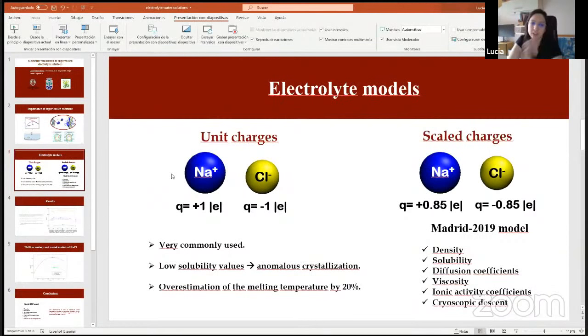Okay, so regarding the electrolyte models, we have unit charge models and scale charge models, and the first ones have been very commonly used, but they provide low solubility values, yielding anomalous crystallization. And one would expect that they at least would provide a good description of the solid state, but they overestimate the melting temperature by 20%.